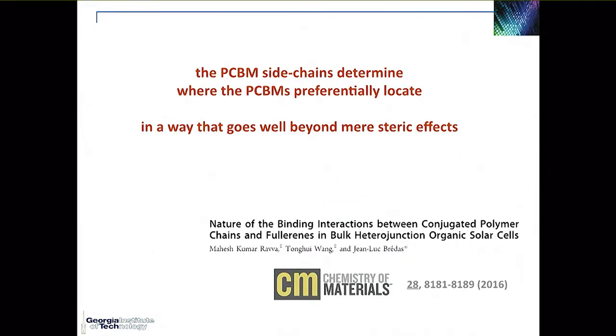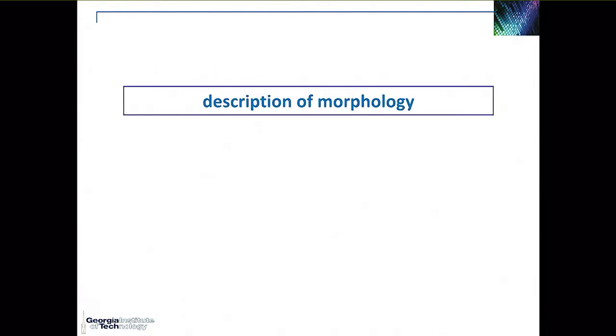So overall, the message is that the PCBM side chains determine where the PCBMs preferentially locate in a way that actually goes well beyond what mere steric concepts would tell you. And then we put also the side chains on the polymer.